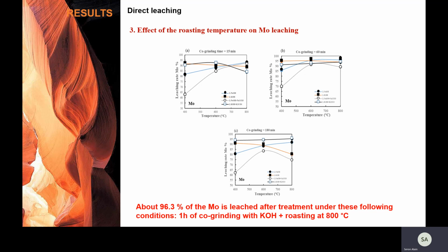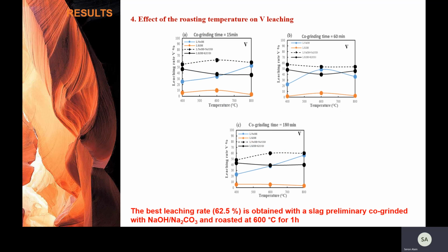Similar observations were made regarding molybdenum recovery. About 96% of the molybdenum is leached after co-grinding with potassium hydroxide for 1 hour and then roasting at 800 degrees C for 2 hours. Considering vanadium, the best leaching rate is higher than 62%. It is obtained after co-grinding of slag with the sodium hydroxide and sodium carbonate mixture for 3 hours and then roasting at 600 degrees C for 2 hours.